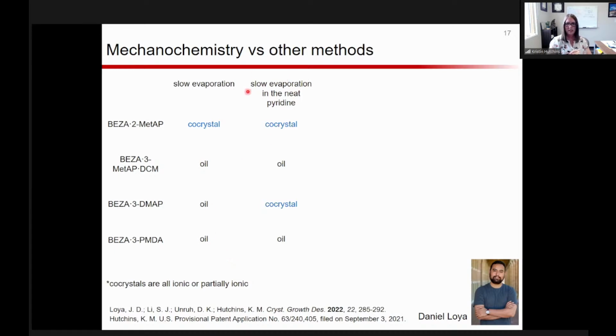And so we also tried slow evaporation in the neat pyridine. So essentially taking bezafibrate and just dissolving it in that neat liquid reactant, kind of similar to that Bill Jones paper I showed you. And in the case of the 2-methyl, we were able to get a co-crystal. In the case of the 3-DMAP, we were able to get this, but we had to use a lot of excess 3-DMAP in order to get this to work.